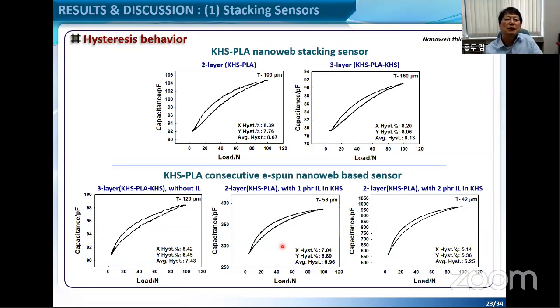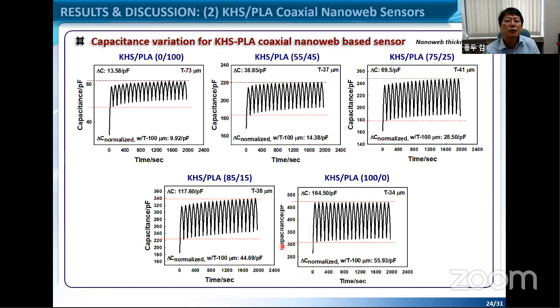Let's move on to the second example, the KHS with the PLA with a coaxial system. In that case, from the PLA 100% to the KHS 100%. So from this PLA case, the capacitance change is very small because, as I told you, PLA has a little brittleness and it is not elastic. It is not an elastic material. Also, it has some creep behavior.